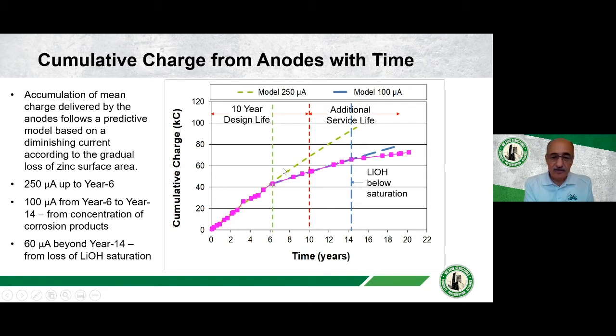The only thing we have to deal with is this little hump here, and we think that we pretty much dealt with that quite well in newer anodes, because we've increased the lithium hydroxide concentration up to about 7 times from that initial one. By doing that, lithium hydroxide is obviously soluble, it's being consumed, and whenever that is being consumed, you open up pores, so there's a lot more porosity available for the corrosion products to get into. So that will most likely be delayed, although we haven't got any data to prove it just yet. That's likely to be the case, and we've dealt with that one by adding additional lithium hydroxide. So hopefully our profiles will follow that green line for much longer.